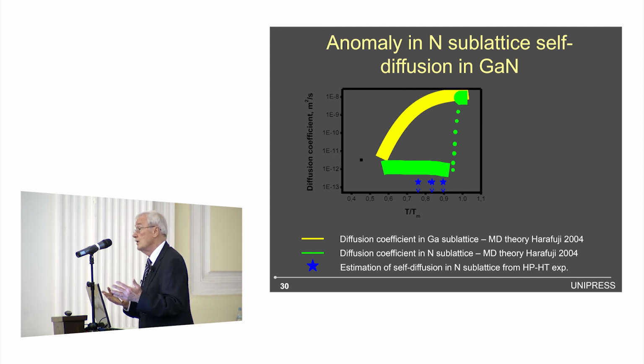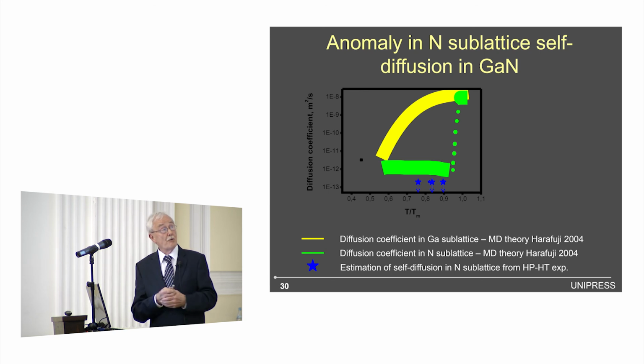The authors were so surprised with this result that they expressed doubts that it is so strange that maybe it is only an artifact due to some computer calculations. However, our data, which are shown here, I will not go into details how this was measured, show that diffusion coefficients are extremely low, even lower than for the gallium sublattice. They are even lower than what was expected by the theory. So that's a very strong argument that the theory really works also for this phenomenon.